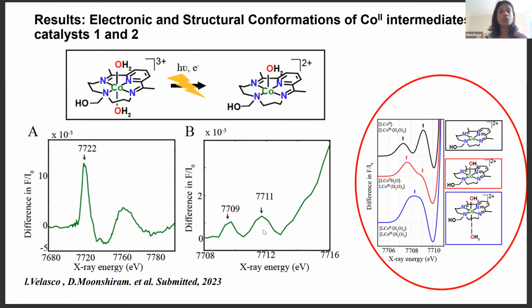Upon light excitation, we observed a typical transient signal, which corresponds to the photoreduced cobalt-2. This has a peak energy of around 7722 eV, which corresponds to the cobalt-2 formation, as well as a broad peak in the negative region around 7730 eV, which corresponds to the decay of the cobalt-3 species. So this transient signal can be measured at varying times at Sector 11-ID-D as well as 25-ID-D, which allows us to obtain the photoinduced kinetics and dynamics of the cobalt-2 species.